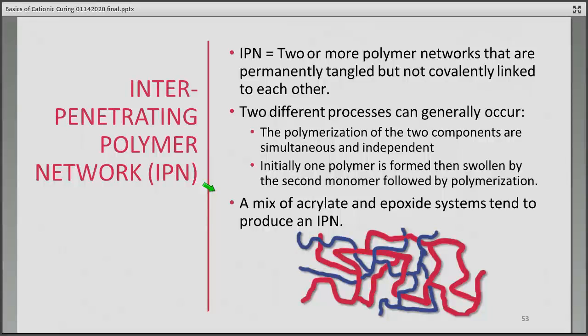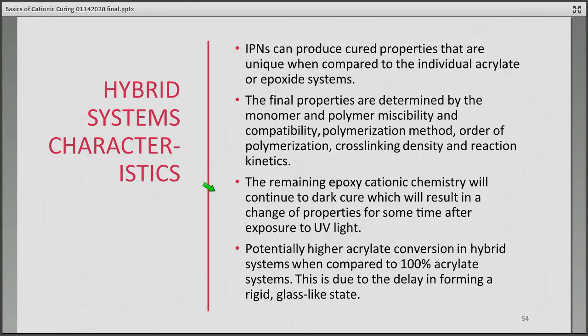Now when you mix acrylates and epoxide systems, they tend to produce IPN. So that tends to be the usual outcome when you blend a free radical system and a cationic system. Why would we want to do that? Well, IPNs can produce some cure properties that are very unique when compared to an individual acrylate or an epoxy system. The final properties are determined by the monomers that you're using and their polymer miscibility, their compatibility, the polymerization method, your order of polymerization, what reacts first, what reacts second, the cross-linking density, and the reaction kinetics.